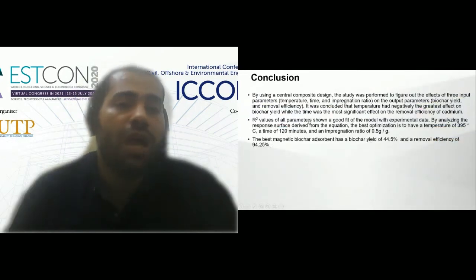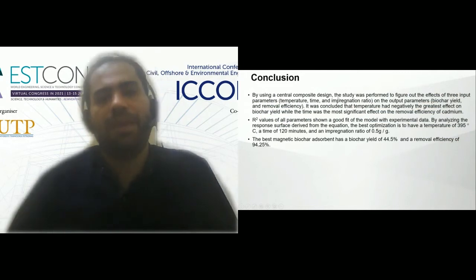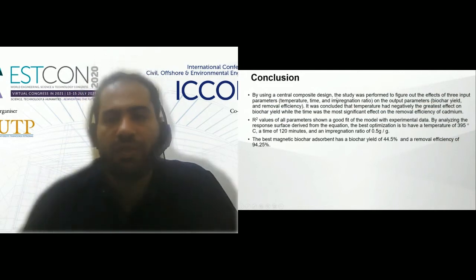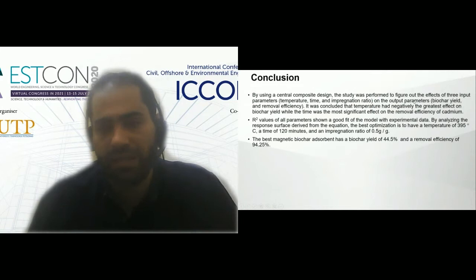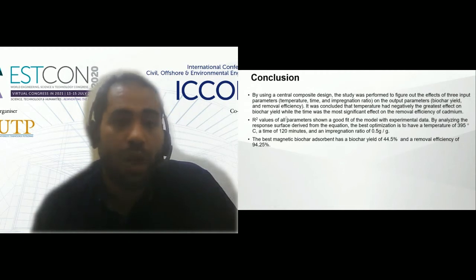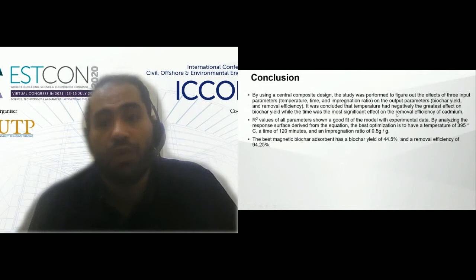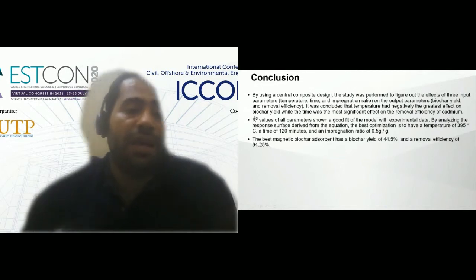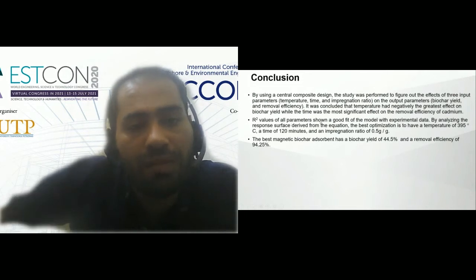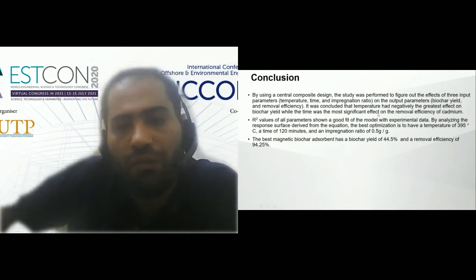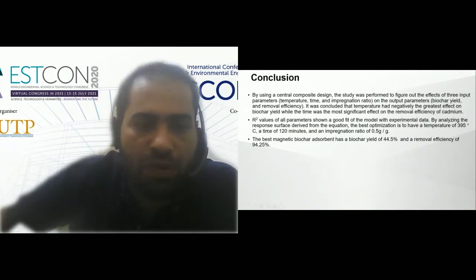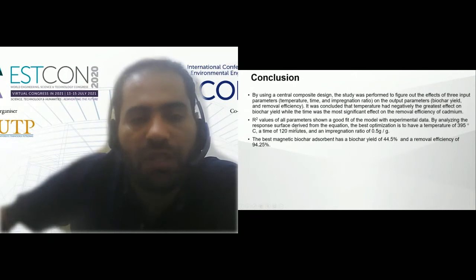We have the conclusion now. Using the central composite design, the study was performed to figure out the effects of three input parameters, temperature, time, and impregnation ratio, on the output responses, biochar yield and removal efficiency. It was concluded that temperature had the greatest negative effect on biochar yield, while time had the most significant effect on the removal efficiency of cadmium. The R-square values of all parameters showed a good fit of the models with experimental data by analyzing the response surface. The response surface methodology derived from the equation.